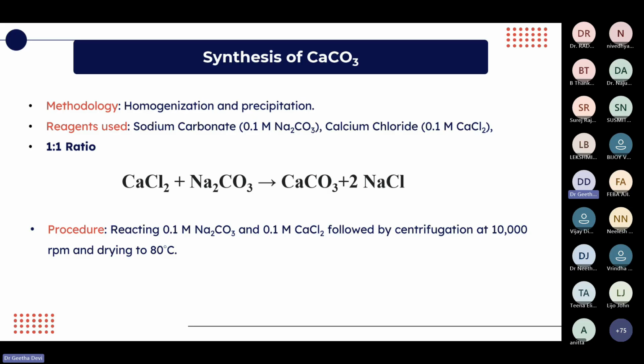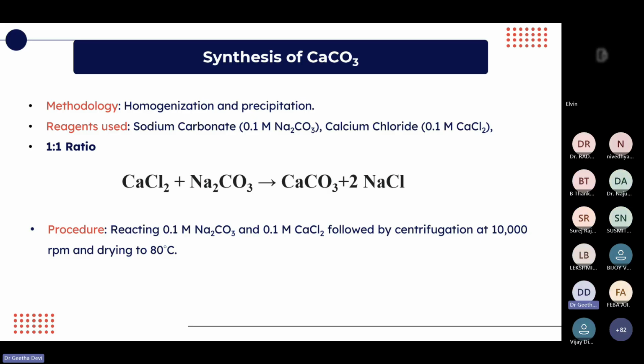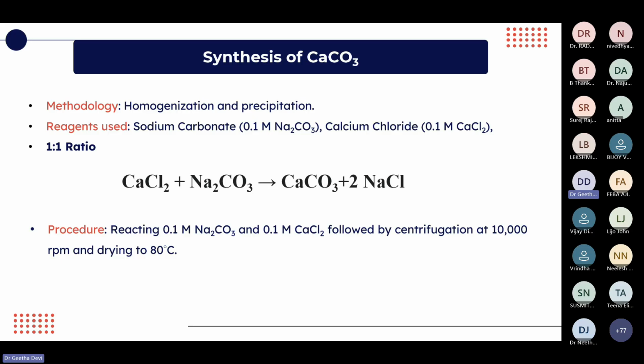It is synthesized by the homogenization and precipitation technique by reacting sodium carbonate and calcium chloride in a 1:1 ratio, and this is the reaction involved in the production of calcium carbonate. It was conducted by reacting 0.1 molar sodium carbonate and 0.1 molar calcium chloride for 20 minutes. Within 20 minutes we were able to get the calcium carbonate, which was then centrifuged at 10,000 rpm, followed by drying at 80 degrees Celsius and made into a fine powder.